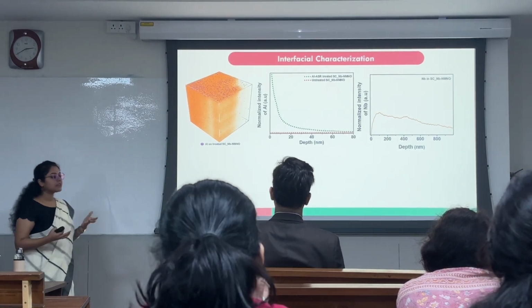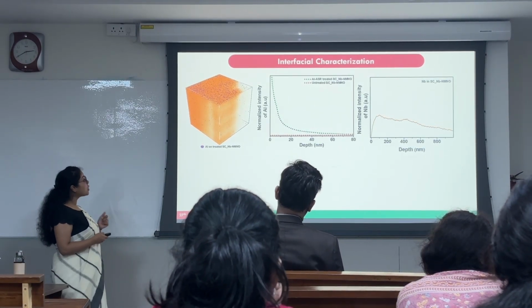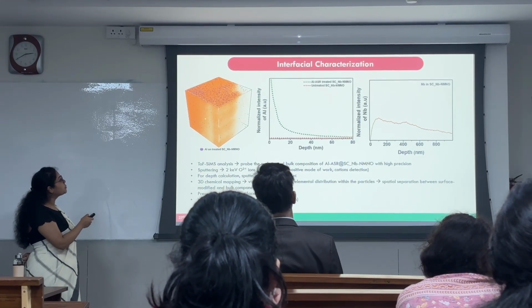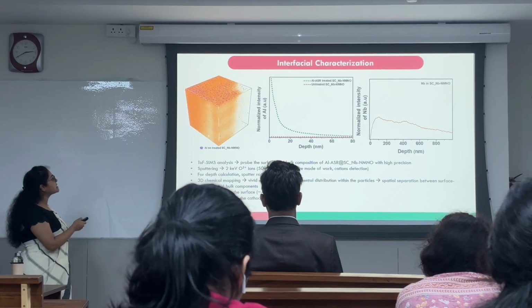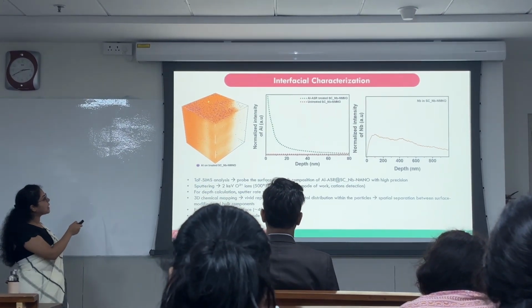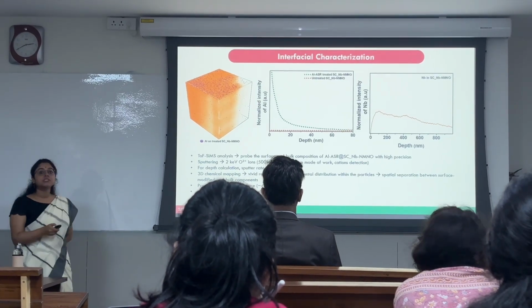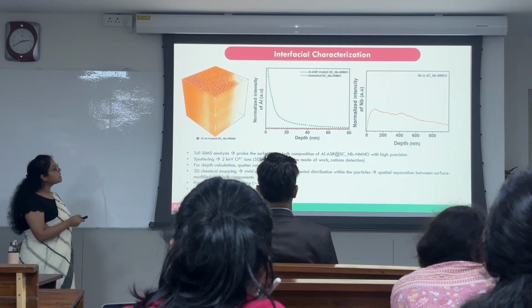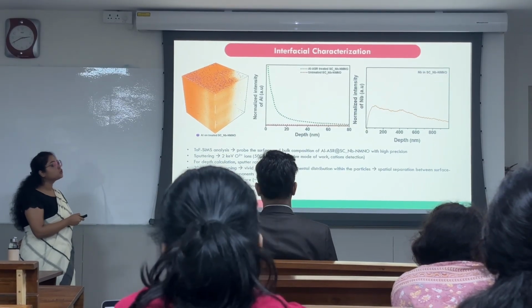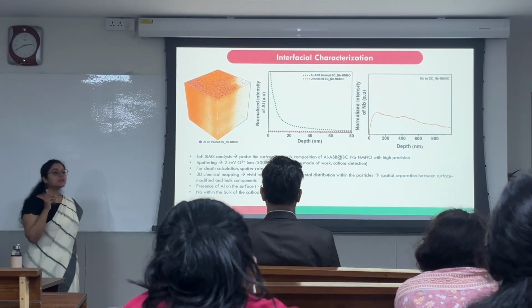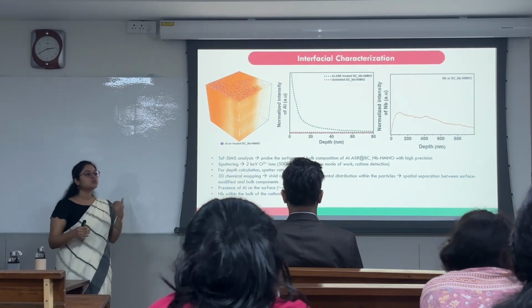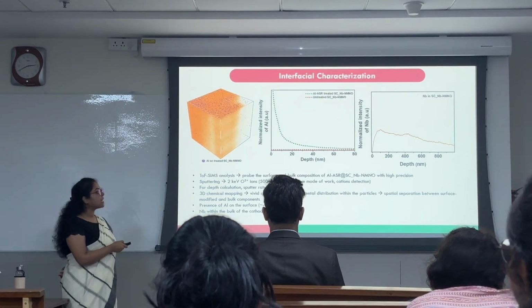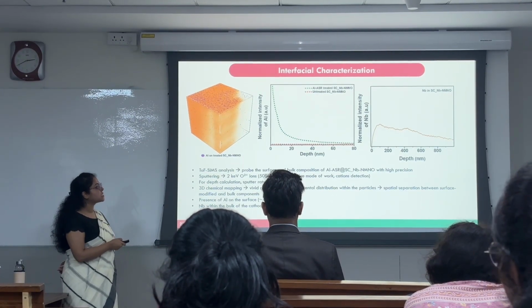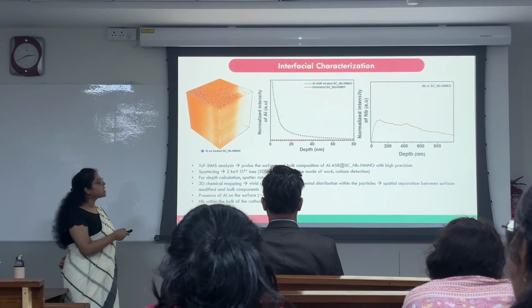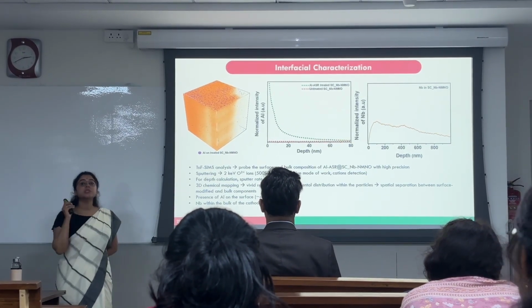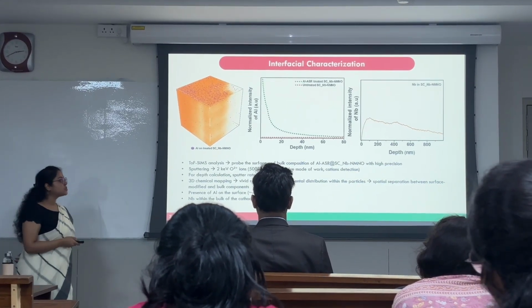So we did interfacial characterization using the TOF-SIMS analysis, and we observed that when we probe the surface and the bulk, aluminium through the 3D rendering map is only there on the surface. In fact, through the depth profile analysis, we observed that the aluminium can be seen only till 40 nanometers, and the untreated one does not show any peaks of aluminium. The claim that the niobium has been uniformly distributed into the bulk was seen through the TOF-SIMS analysis as well, which shows the presence of niobium throughout the crystal, starting from around 5 nanometers, which shows that niobium is not undergoing any kind of atomic scale surface reorganization.